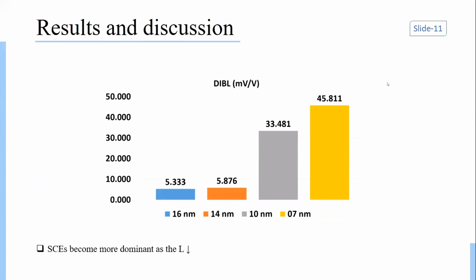These bar graphs show that when channel length is 16 nanometer and 14 nanometer, the DIBL is almost negligible, and when it shrinks to 10 nanometer and 7 nanometer, the DIBL increases significantly.